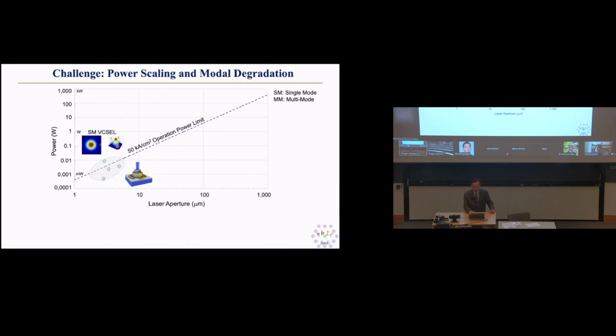You can see this nice Gaussian beam here. When your aperture size is a few microns, whether it's a VCSEL, or an edge emitting laser with a ridge waveguide structure of a few microns. By the time you get over 10 microns or so, it becomes so-called multi-mode. So the mode quality degrades, and then it results in lots of issues and challenges in terms of application, like degrading your performance, because it becomes multi-mode.